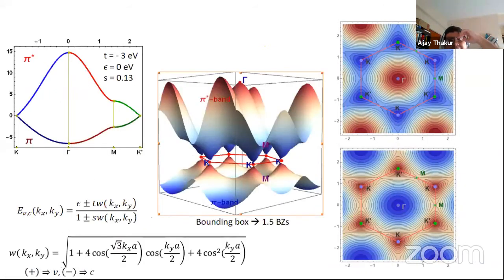If we try to plot it, this particular plot was generated using Mathematica this morning for this talk. And you can see that one can have these 6 nearly equivalent points. First of all, let me tell you that this bounding box corresponds to about 1.5 times the Brillouin zone. So the points at which we are marking the ends of a hexagon correspond in this picture to about plus pi by a and minus pi by a. The extreme values correspond to plus pi by a and minus pi by a. And what we have done is we have created a bounding box which is about 1.5 times this Brillouin zone, and we find these 6 equivalent points here, which we will call the K points or the K prime points.